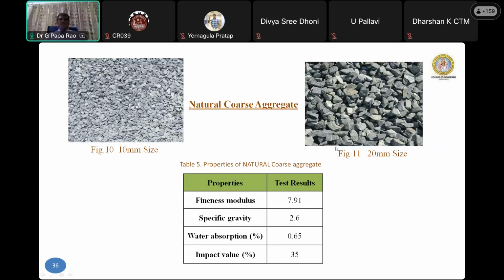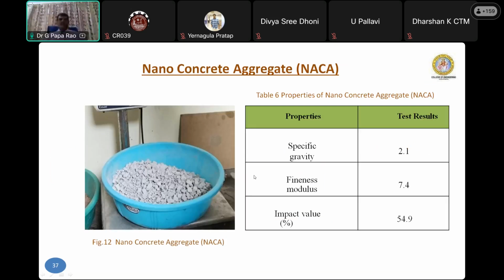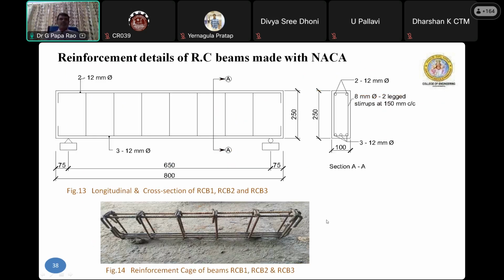We have conducted the tests for our natural aggregate as well as nano concrete aggregate. For the nano concrete aggregate, the specific gravity is 2.1 and the fineness modulus is 7.4. If you observe the impact value, I told you we can make up to M80 also with this proportion. So here the impact value also we have observed as high, 54.9, as against 35% in our natural aggregate. So easily we can use this material as aggregate for roadworks also, because it possesses a high impact value.